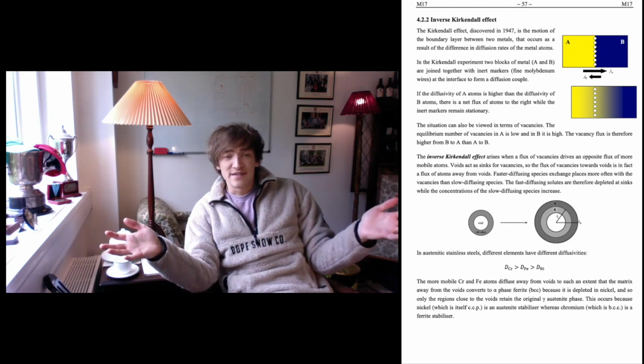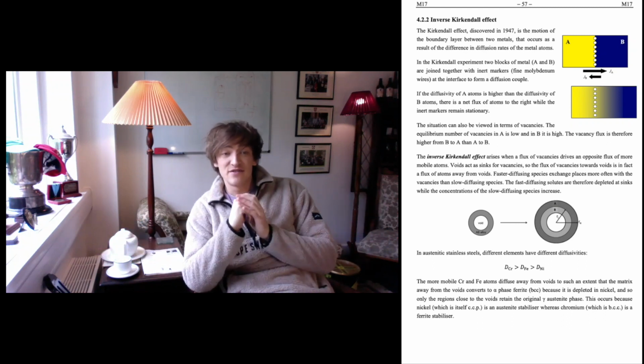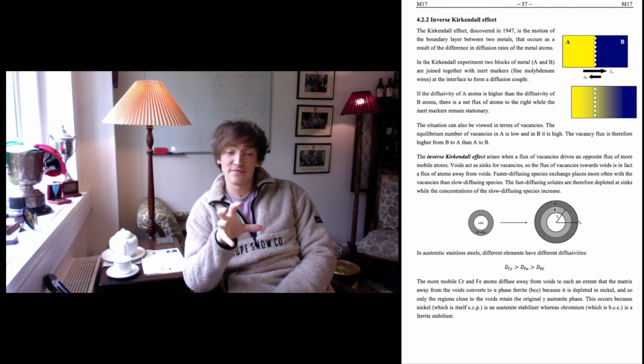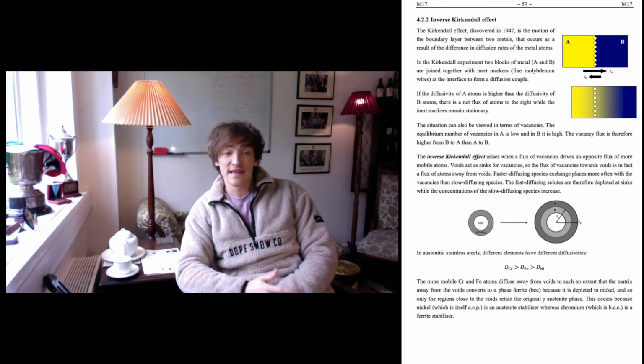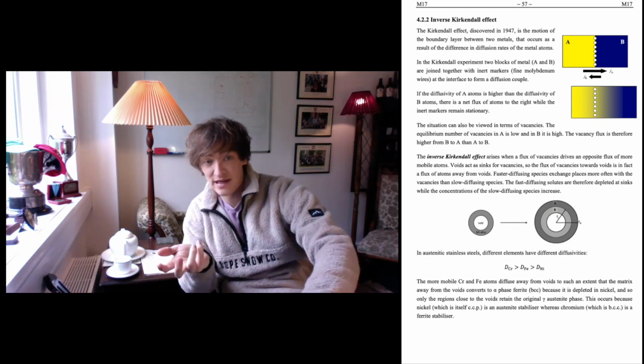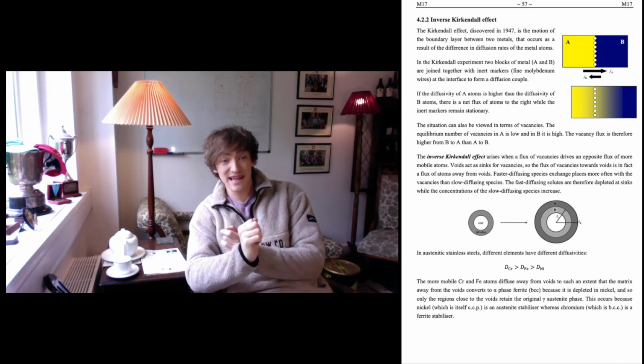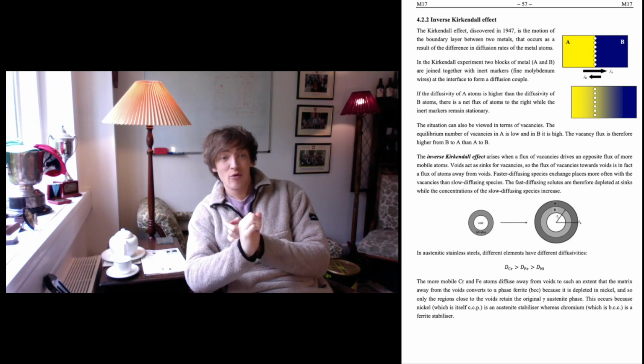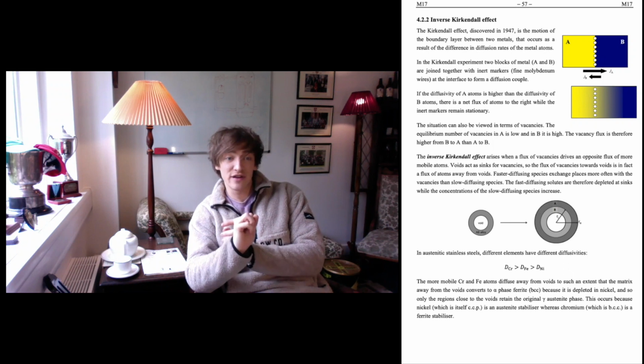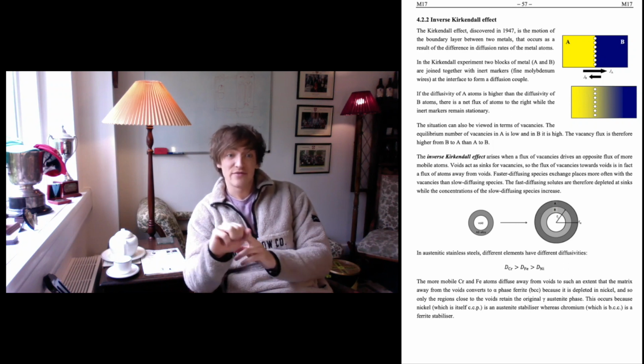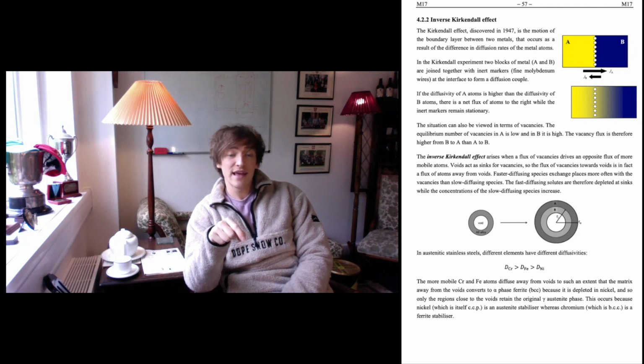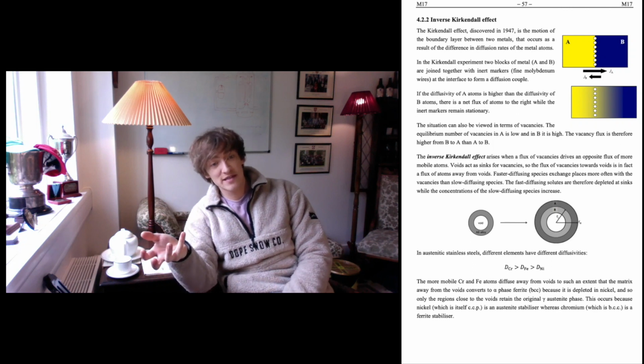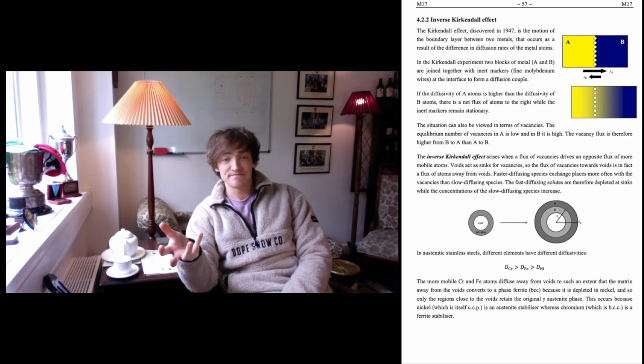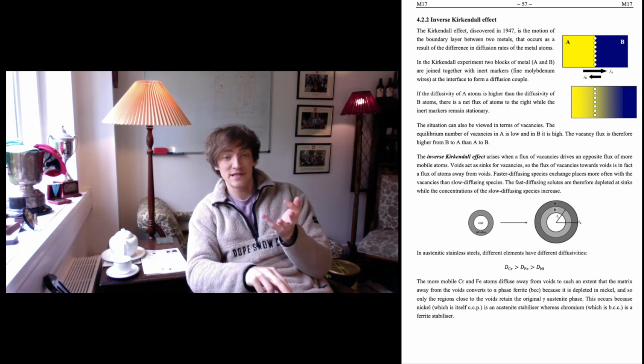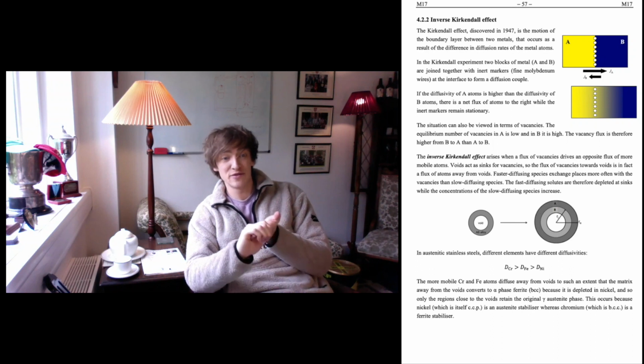So why are we interested in this? What does it do? Well, when a flux of vacancies drives an opposite flux of mobile atoms, in this case A atoms, we call this the inverse Kirkendall effect. The results of which are faster diffusing species become depleted at vacancy sinks, whereas the concentration of the slower diffusing species increases at the sink. So in stainless steels containing voids, you can get significant variation in composition surrounding a void. And what happens when you have significant changes in composition? You can get phase transformations. And phase transformations lead to different mechanical properties, corrosion properties, etc., which we do not want.